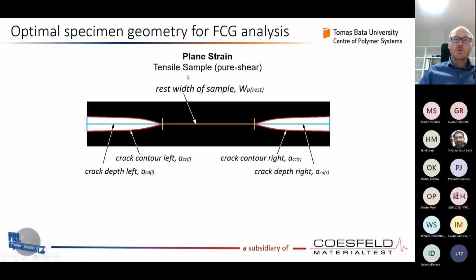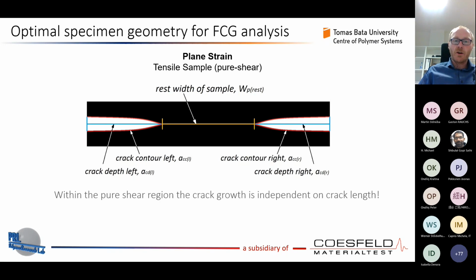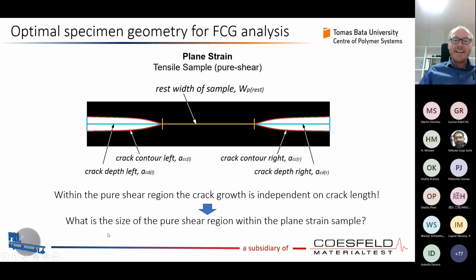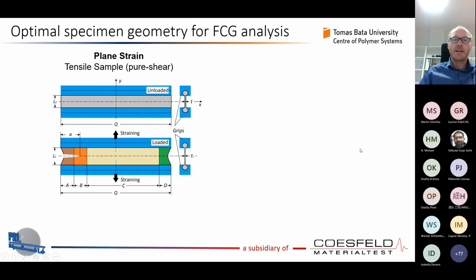So the plane strain is an optimal sample for the crack growth characterization or measurement, because within the pure shear region, the crack growth is independent of the crack length. That means we need to ask, what is the size of the pure shear region within the plane strain sample? And is there any pure shear region? These are the main questions.